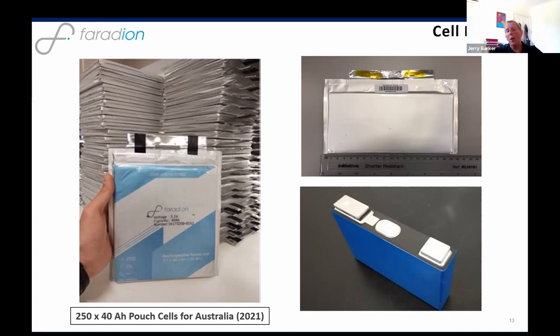So those 40 amp hour cells have a nominal discharge voltage of about 3.1, so you can see somewhere between 120 and 130 watt hours. So you can kind of see what they're looking at. And you can see along the top that they're shorted, ready for transportation. Couldn't do that with lithium ion.